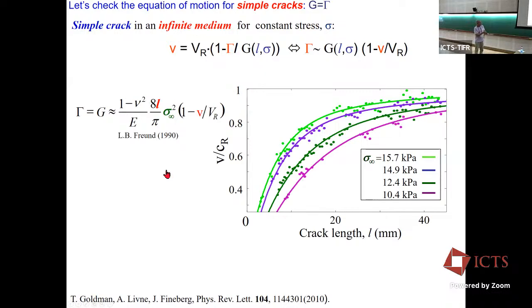So the first thing I want to show you is the equation of motion that we derived before. This is it in nasty detail, but it's dependent on the fracture energy. This is the fracture energy again. It depends on the instantaneous length of the crack, and this is the velocity. So this is the velocity as a function of the length of the crack. For each one, the different colors are different stresses that we applied at infinity. The points are the data, and the straight lines are the theory with no adjustable parameters. So once we've gotten rid of all of the things that we don't understand, it tells us that the theory understands very well what's going on.